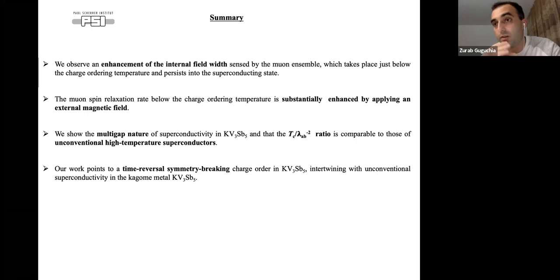Yes, that's a really good question. So what's the simple physical picture? I think muons are not sensitive to, let's say, charge density wave transition. But now there are two things. When we do experiments in zero field, muons see the increase of the internal field widths, but at the same time we see also a change of the nuclear relaxation rate.